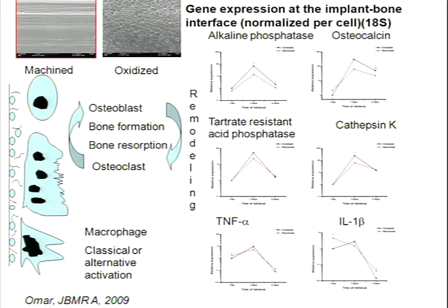Furthermore, we have inflammatory cells present. These cells typically express cytokines, tumor necrosis factor alpha, interleukins, etc. We have two examples here, TNF-alpha and interleukin-1 beta. That expression is higher on the smoother surface. What's the explanation?